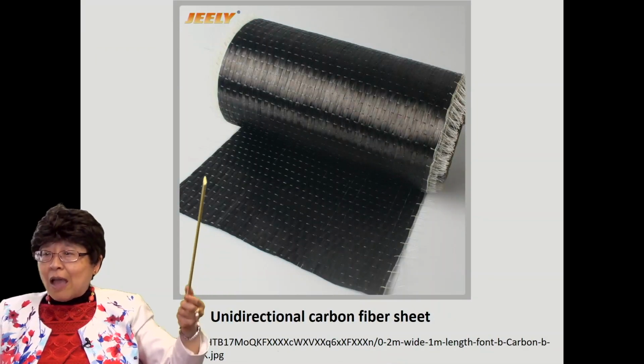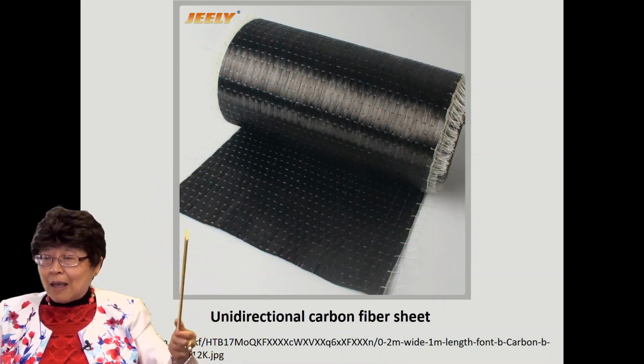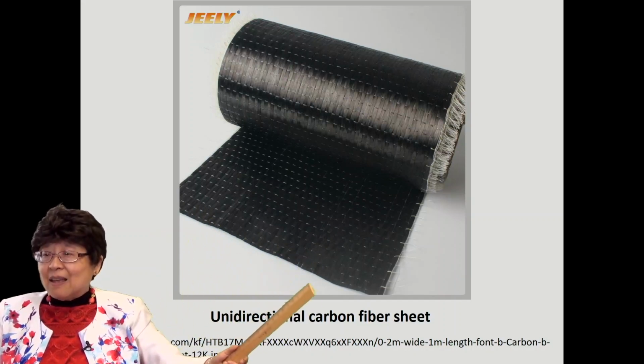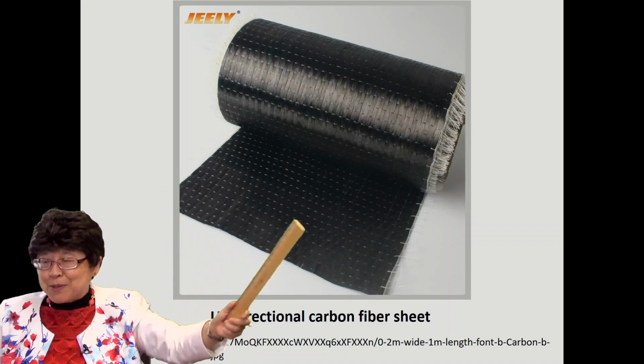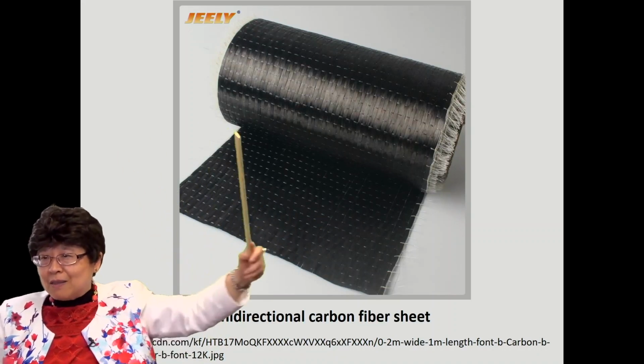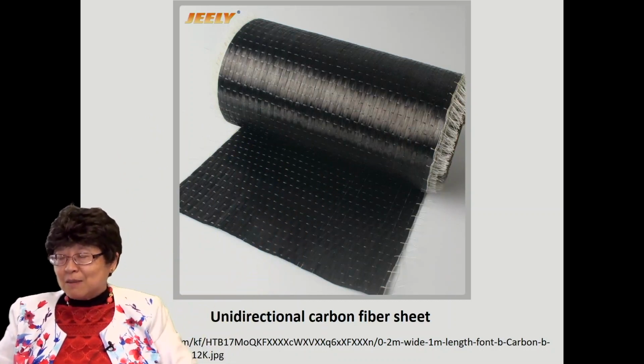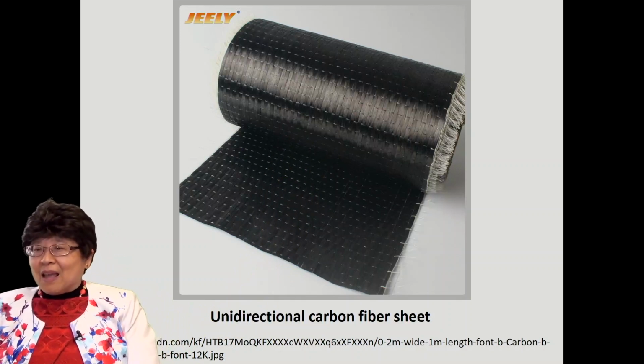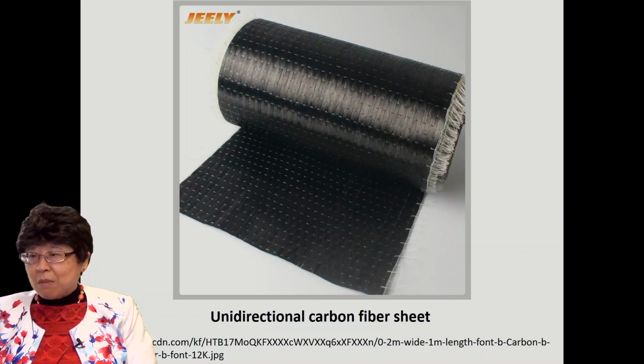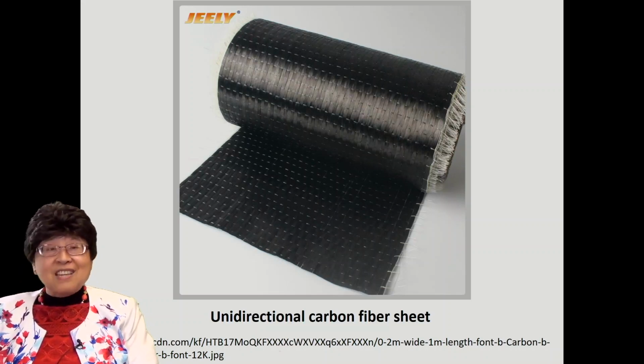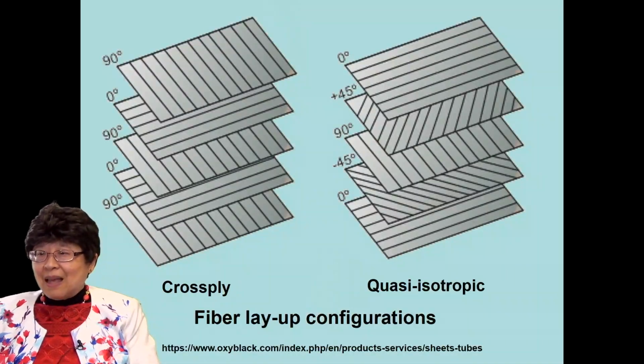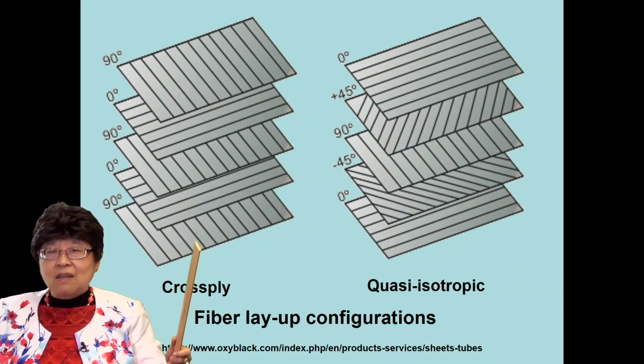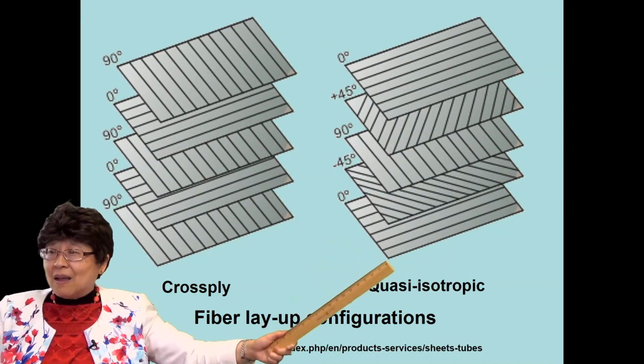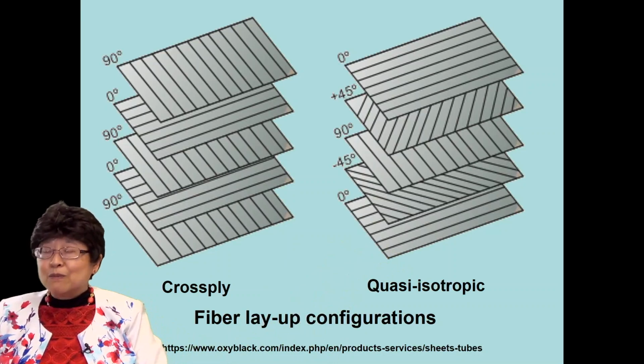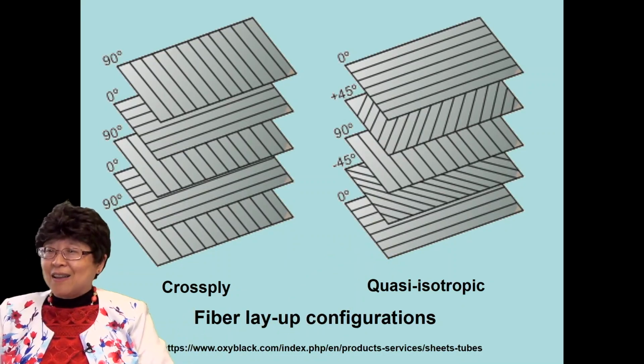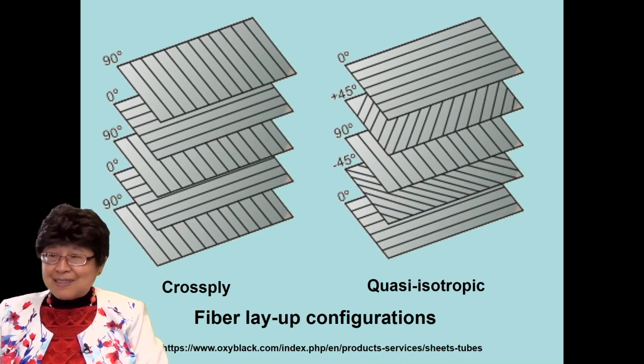Another form is you have the carbon fibers lined up, and they form a sheet, okay? And they can use some sewing to make the fibers not spread out too much. Okay, the fibers are in this direction here. Okay, the sewing is in the perpendicular direction shown in yellow. So this unidirectional carbon fiber sheet is convenient for being stacked to make a laminate. Okay, and you can stack in different orientations for the fibers in the different layers. Okay, and we call this the fiber layup configuration. And so it's up to the engineer. I want it stronger this direction, stronger that direction. You have a choice.